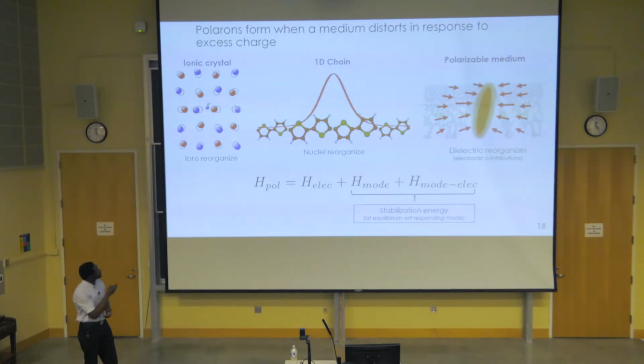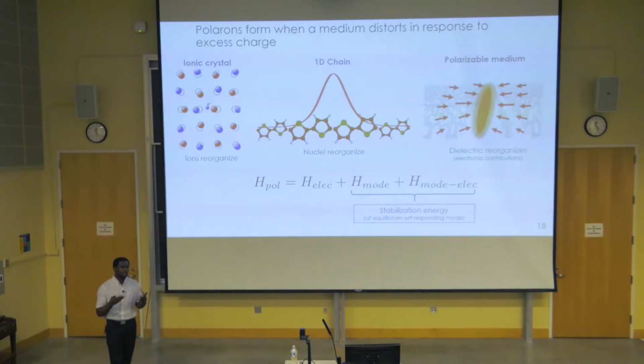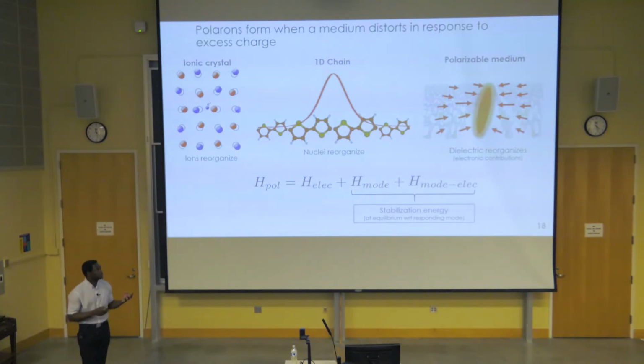We have the energy of the excess charge, the energy of the responding modes within the material, and the interaction between the responding mode and the excess charge. And at equilibrium with respect to the responding mode, these two terms give us the stabilization energy that occurs as a result of this phenomenon of polaron formation. So over the next four slides, I'll look at the polarons that arise through the reorganization of nuclei and the polarons that arise through the reorganization of the surrounding dielectric.